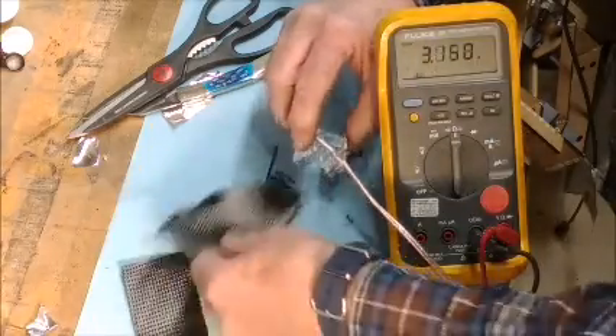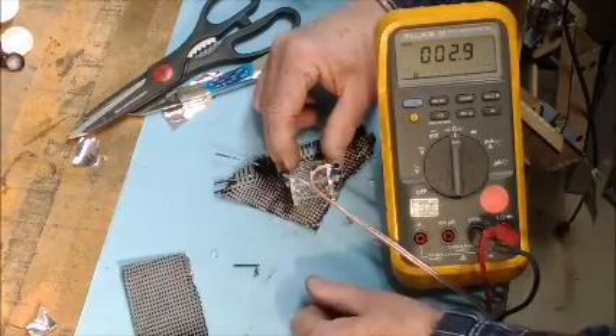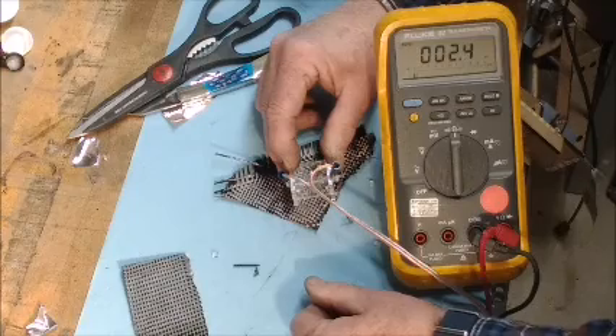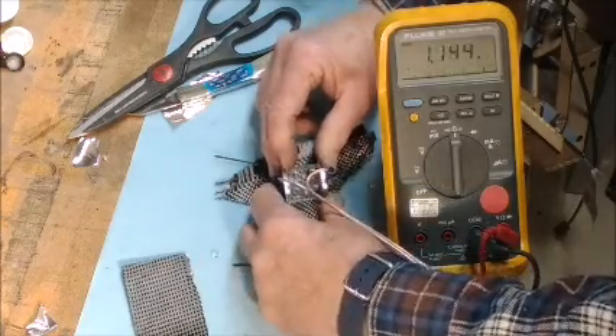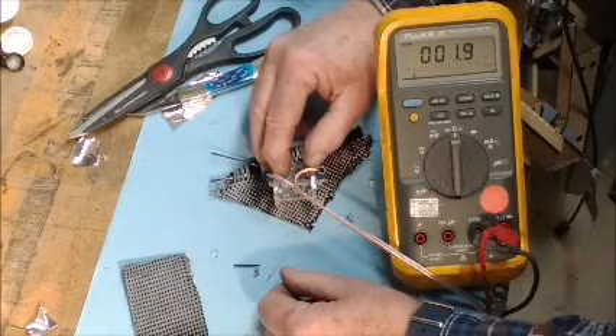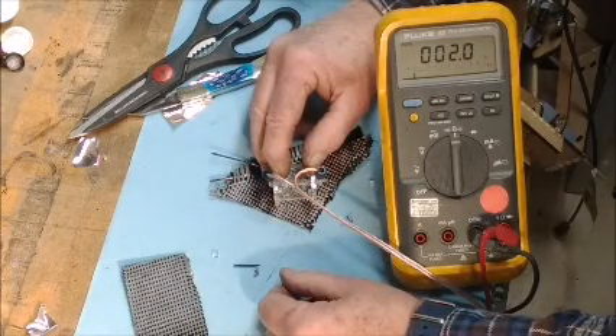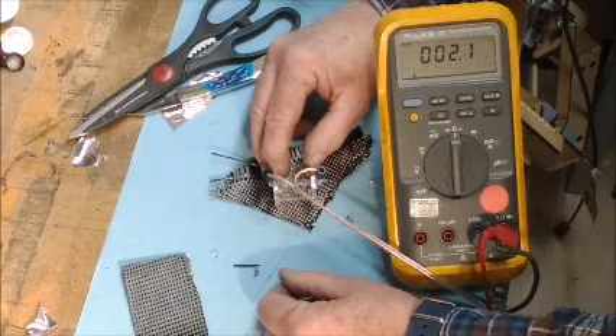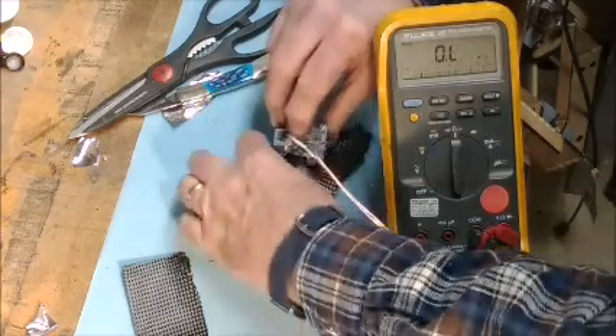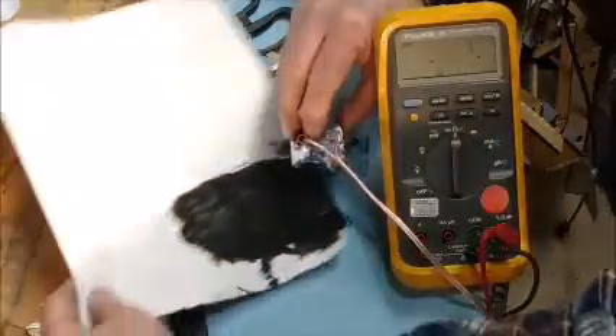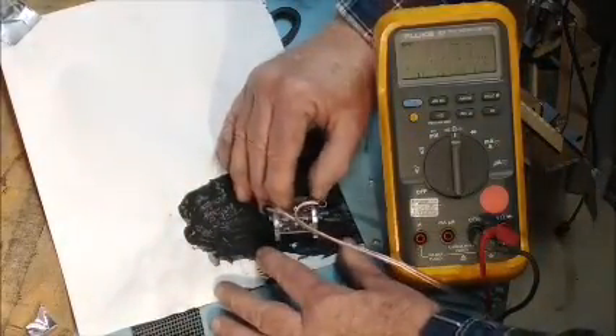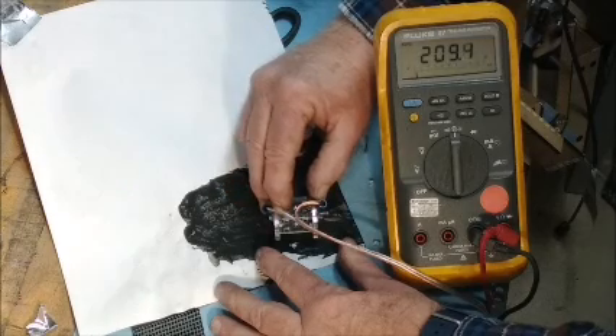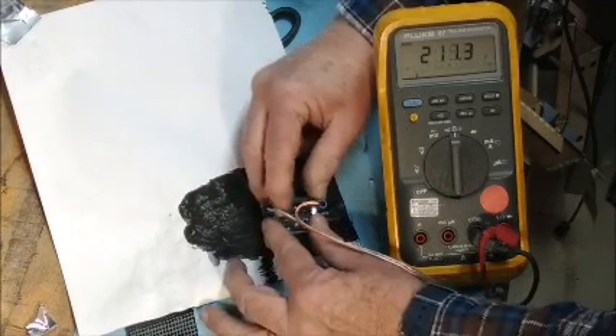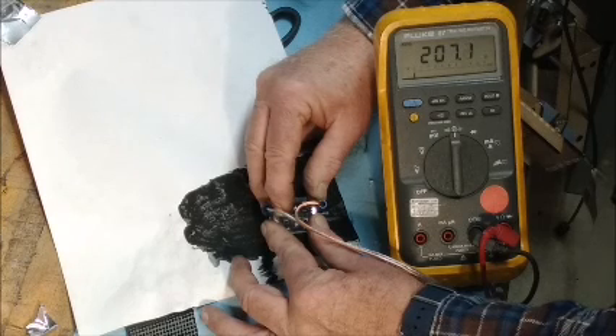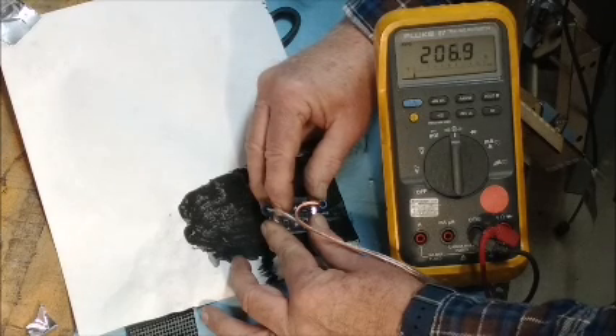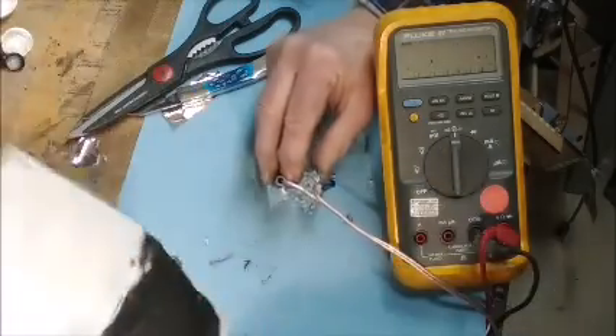Let's see which material is which now. Yeah, you'll take it down just about half. Okay, so you can increase the conductivity, cut the resistance in half just by baking it in a kiln. There's 2 ohms right there. There's some carbon-coated paper. Oh, that's really a crummy carbon, 210 ohms per square. That's not good for much other than taking nice white paper and making it black. Not a very good conductive ink.